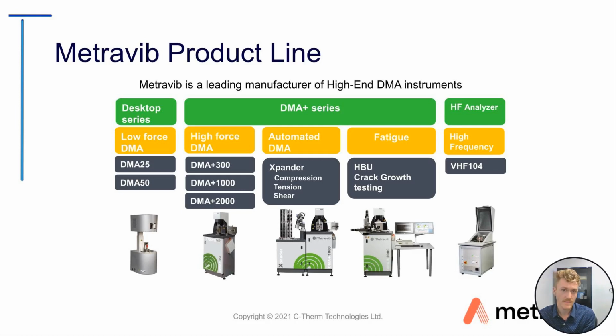Under high force DMA, we have DMA Plus 300, 1000, and 2000, which refers to the peak to peak load that's able to be provided. So 2000 newtons peak to peak for the DMA Plus 2000. Additionally, we have access to Xpander, which is able to do automated testing 24/7 in your lab on compression, tension, and shear testing of materials. And finally, we have fatigue testing, in the form of heat buildup testing and crack growth testing, which are methods that I will explore a little bit more in this talk.